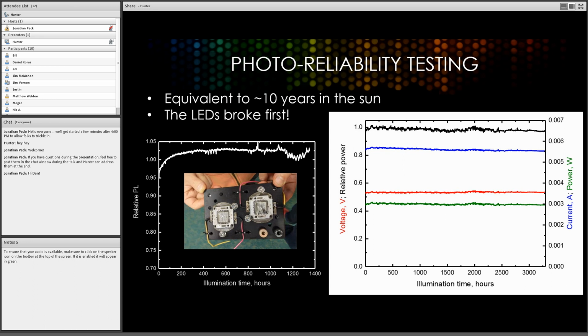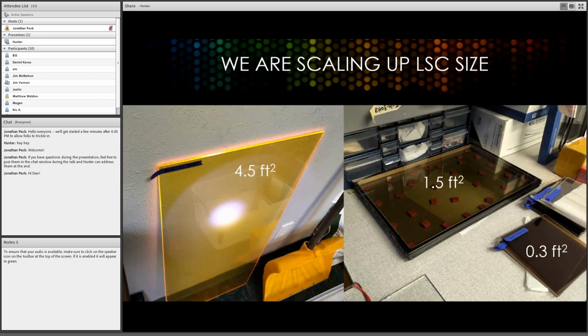Of course, we're working to push that further and really understand how we can accelerate degradation. And it's challenging for various reasons, the least of which is that the actual real world is one sun. If you crank up the temperature or the intensity, you can introduce nonlinear effects that are not representative of what will actually happen. And sometimes, like on this bottom left one, when you crank it up too much, other things might fail in your tests, like these LEDs. These very high power LEDs actually broke first before the sample did, which is kind of encouraging, I guess.